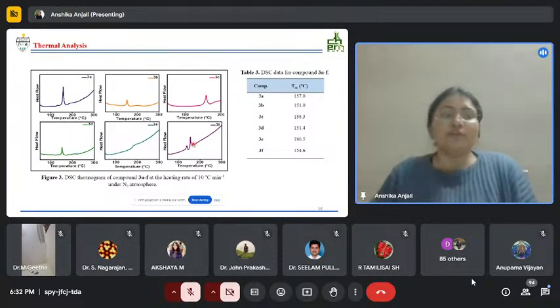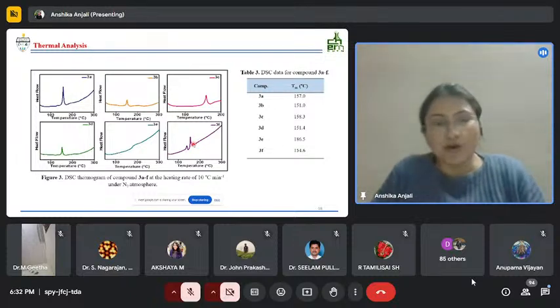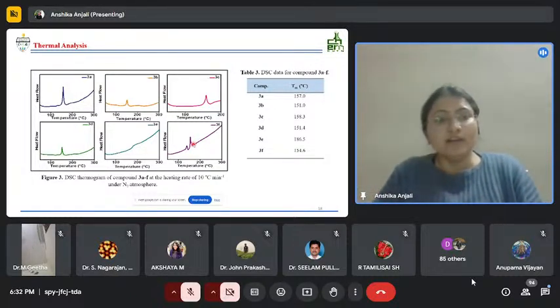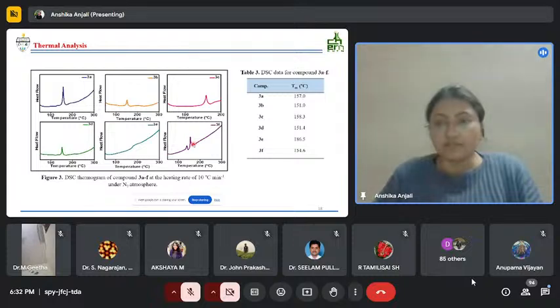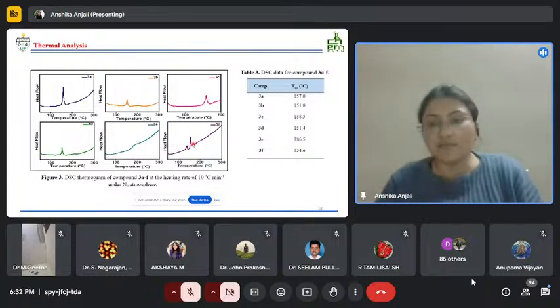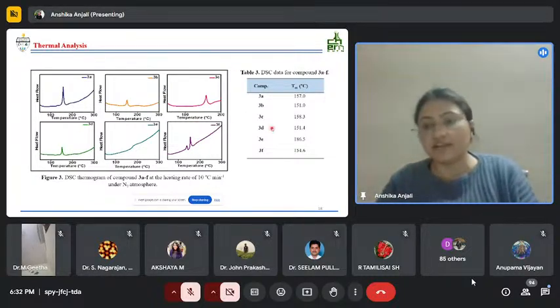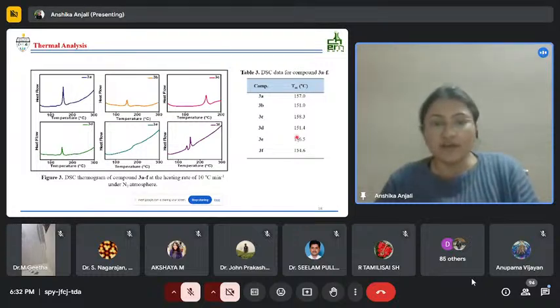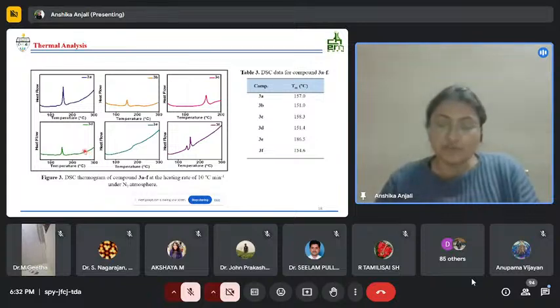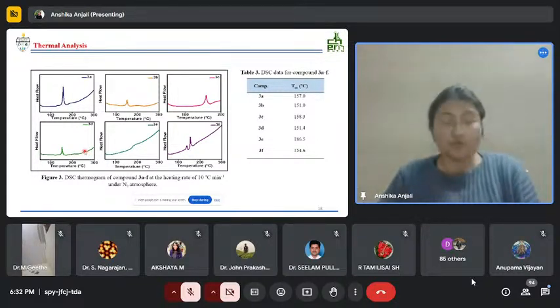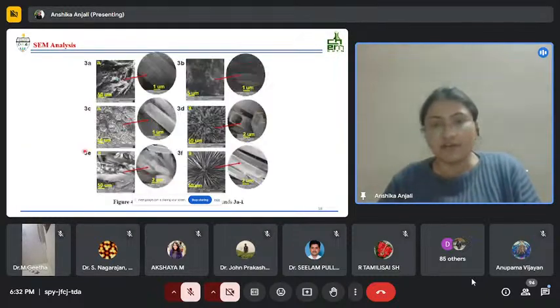Obviously, for the durability and stability of any organic compound, thermal stability is really important. For that, we have recorded their DSC thermograms. We have done the differential scanning calorimetry technique to determine the melting point. Here, all these compounds were thermally stable with melting points higher than 151 degrees Celsius. Compound 3E, with the 4-methoxyphenyl group as the end group, resulted in the highest melting point.